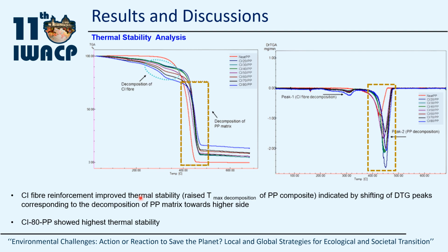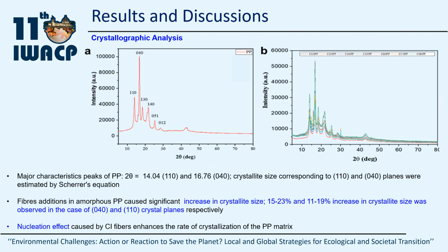The crystallographic study was carried out using the X-ray diffraction technique. The left-hand side shows the X-ray diffraction spectra corresponding to neat polypropylene composite, whereas the right-hand side shows the X-ray diffraction spectra of 7 different mix ratios. The crystallite size was calculated using the Debye-Scherrer equation, and it indicated that the fiber addition in amorphous PP caused a significant increase in crystallite size.